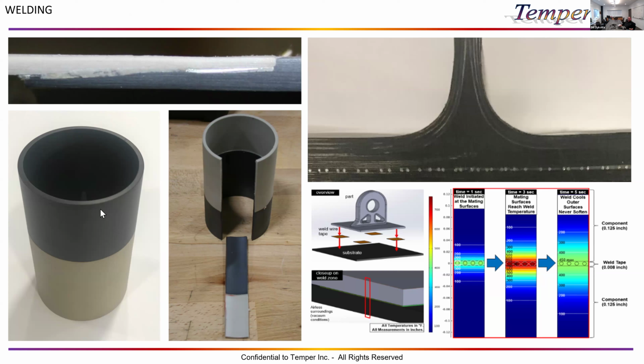This part here is a PEEK part with carbon fiber. The brown part down here at the bottom was PEEK with fiberglass, and you can see the weld. And for instance, if you wanted to weld in space, you could take this bracket, you could pre-put these little patches onto the bottom of it and use a robot to weld it together.